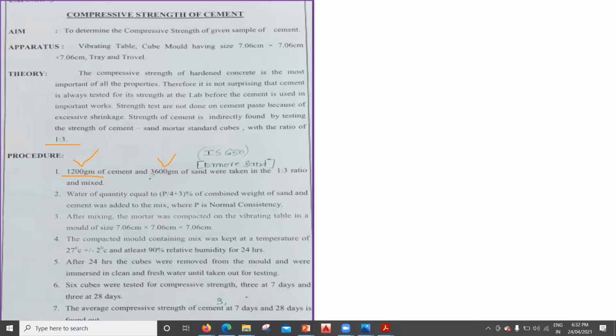The second is that water of quantity equal to P/4 plus 3% of the combined weight of cement and sand was added to the mix, where P is the normal consistency. After mixing, the mortar was compacted on the vibrating table in the mold of size 7.06 by 7.06 by 7.06 centimeter, and then the compacted mold containing the mix was kept at a certain temperature. This is not so important; it's okay if you keep it at normal temperature.